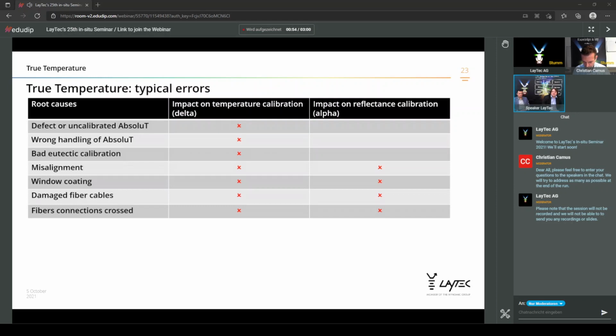In principle, you may get the impression at first glance that the EPITT is still working, but in fact the entire balancing and calibration and consistency of the amount of light is completely disturbed with crossed fibers. As a side effect, this will definitely have an impact on delta and alpha calibration. The calibration sequences will still run and reveal a delta and alpha result, but the results will definitely be wrong. And that will definitely ruin any true temperature in the system.